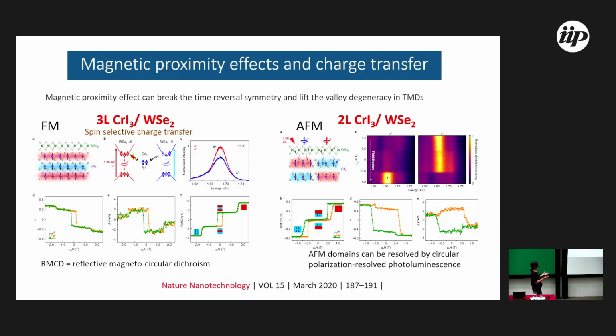So proximity effect, let's review. There are some previous works about proximity effect, but most of the works were performed with magnetic materials that have perpendicular magnetization, because only perpendicular magnetization can break the valley degeneracy. You need perpendicular magnetization. And this is similar to a magnetic field, so you can have a splitting at 0 Tesla, which is very interesting. You don't need a cryomagnet that is very expensive. So people have shown this, there are a few works.